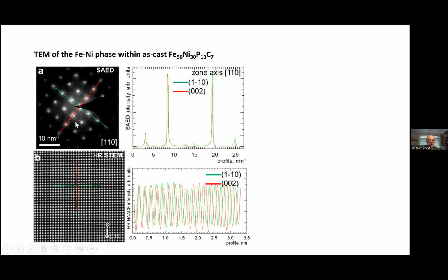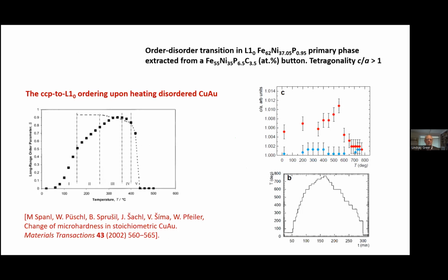This is a diffraction pattern. It tells us about the shape of the crystal unit cell, and the tetrataenite cell is not cubic, but it's very nearly cubic. It deviates from cubic by only 0.7%. So the point I want to make is that if you looked at this pattern and you did not look very carefully, you might well imagine that it was cubic, and that would not be interesting. But it turns out closer inspection shows that the distances in the patterns are not all the same as each other. This pattern is not an exact square. It's very slightly rectangular, and again, it would indicate possible tetrataenite.